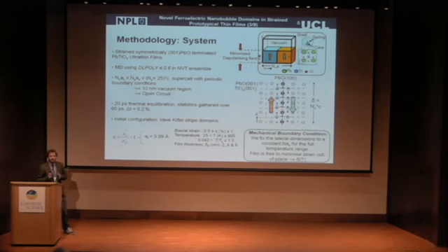Okay, so like I said, I wanted to look at these PTO thin films. There's quite a rich amount in the literature, so I wanted to check this. So how do I set it up? Well, first off, I wanted it to be PbO symmetrically terminated because this is the more stable termination, which has been observed in the literature, and we also check for our force field.